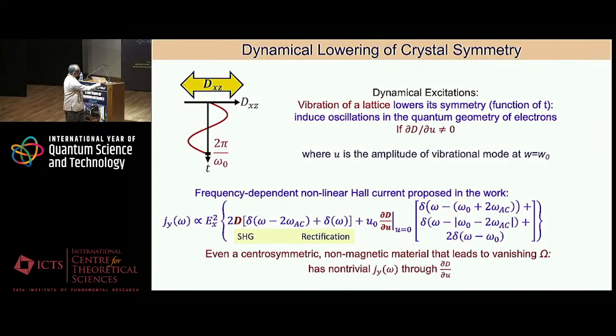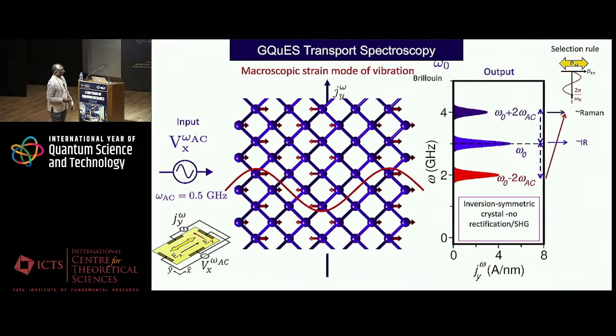The first two terms Mandar talked about are the nonlinear Hall effect, which gives zero frequency and second harmonic generation. But this part is new, which says there will be additional modulations linked to the vibrational frequency plus or minus 2 times the applied frequency, and also the peak at omega 0, which is associated with the rectification part of the nonlinear response. So this can be done in transport spectroscopic mode.